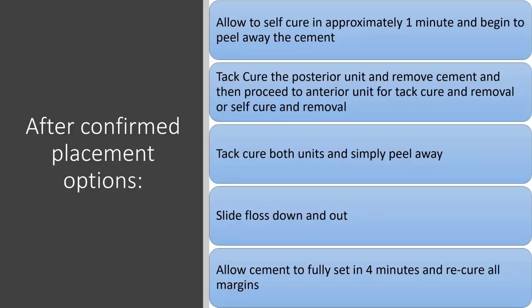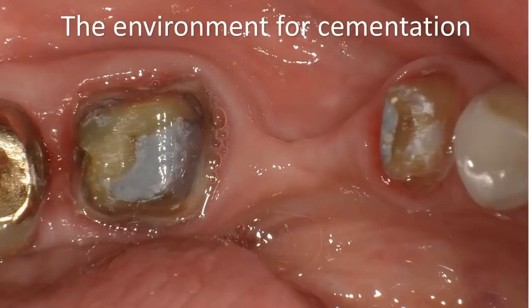So what do we do again? I tack cure, I peel, I relight cure for approximately 2 to 3 seconds. I'll remove any excess cement that I can, and then I'm flossing down and out. You must let the cement set fully for 4 minutes. But this is the environment you cement in. That's it. You got a little inflammation, you're subgingival.